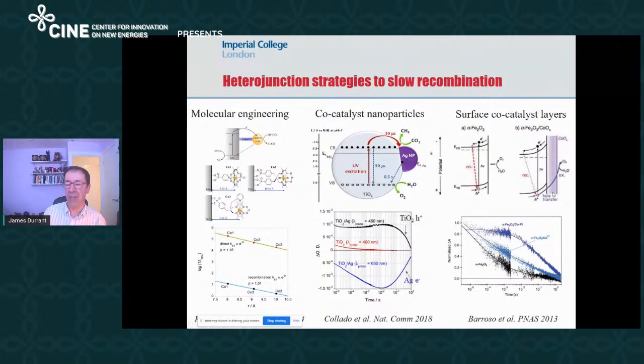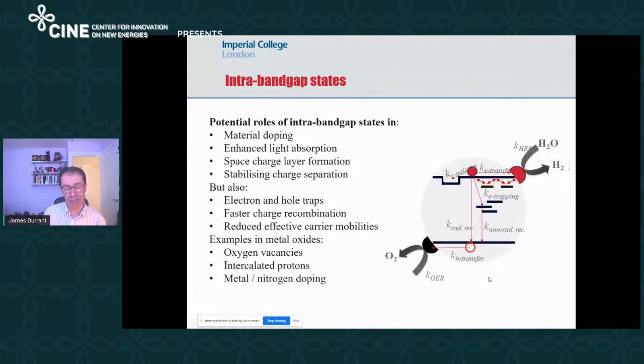Another particularly controversial example is when you put co-catalysts on the surface of hematite. In this case, we're putting cobalt phosphate on the surface of hematite. And what you observe is you don't need so much voltage to drive the water oxidation. And we observe that the carrier lifetimes, just measured with no bias, get much longer, just by putting the layer on the surface. Part of this lifetime gain is because you actually create a Schottky junction between the rather metallic catalyst and the semiconductor, which increases band bending. In some cases, you get a gain in lifetime because the holes directly transfer to the catalyst and then go on to drive oxidation from the catalyst itself. So those are all approaches which are interesting to gain lifetime without requiring so much voltage input.